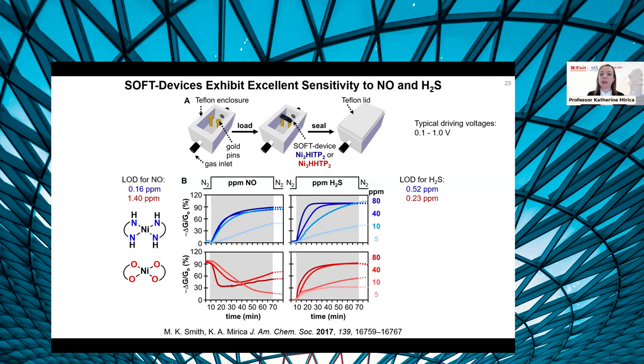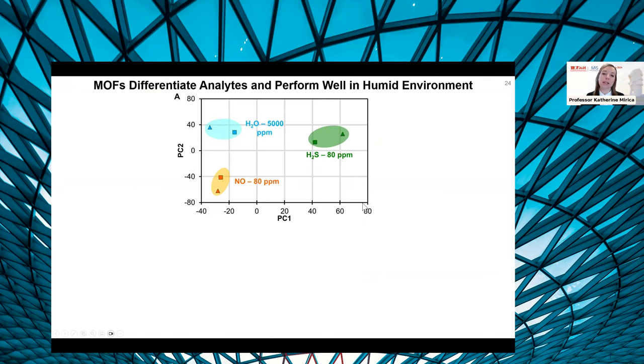So this difference in the directionality of the response and the concentration-dependent response is useful because we can take this two-sensor textile array and then perform principal component analysis, showing that we can achieve differentiation of these gases from each other at part per million concentrations, as well as from the water vapor.